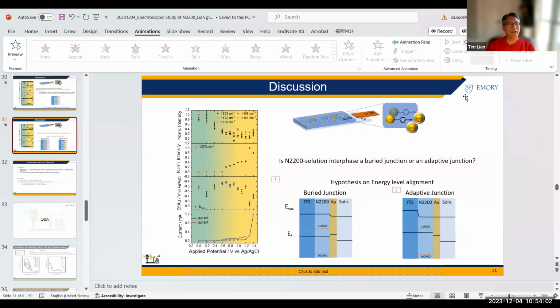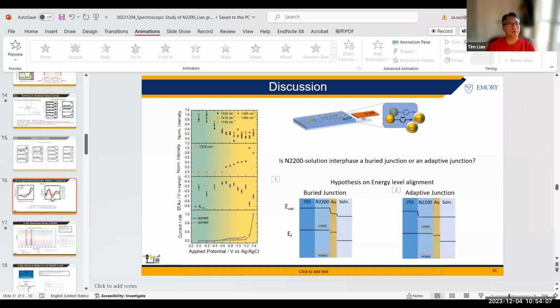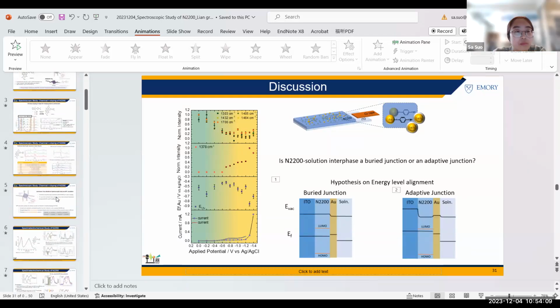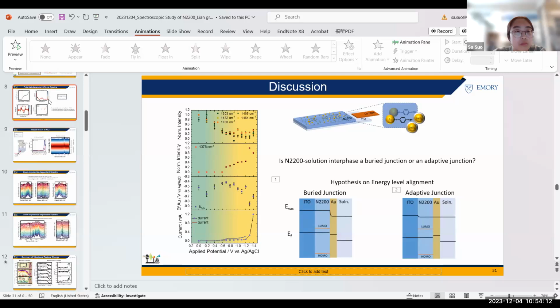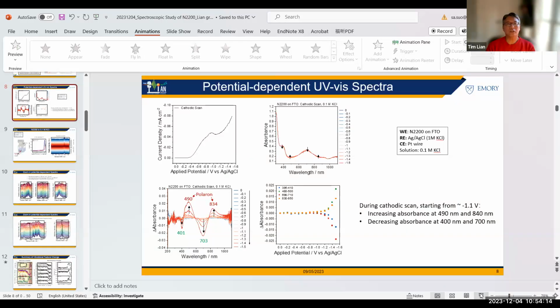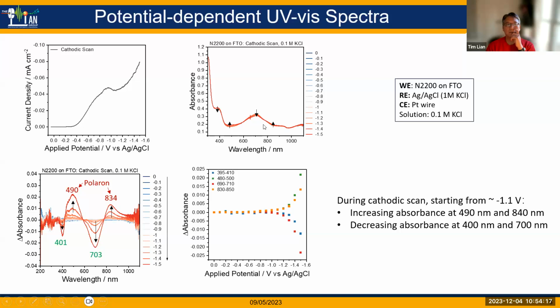So can you go to the slide where you show the UV-vis spectrum before you subtract them? Yeah. Here. Yeah, so you can see the change is actually pretty small. So that indicates a very small portion of the film is actually reduced. And I would expect that to either be, again, this aggregate, or maybe only the top couple nanometers of the film that are even being reduced.